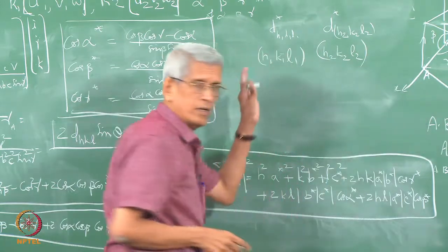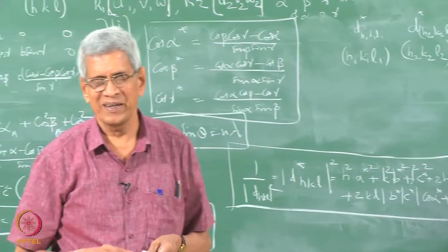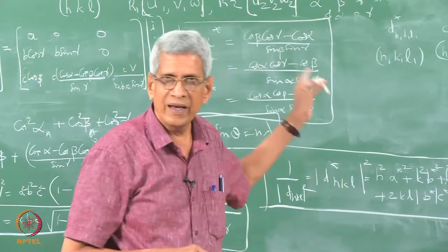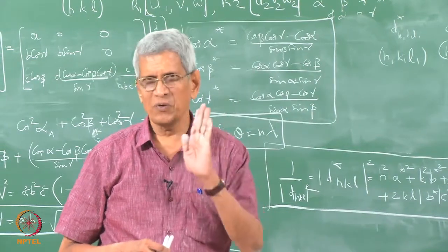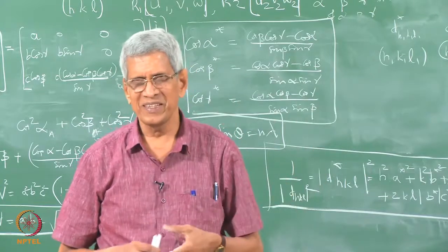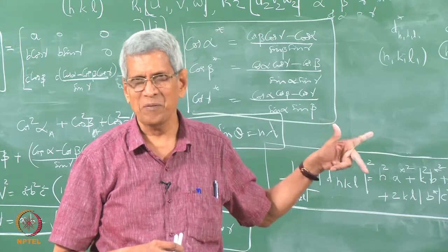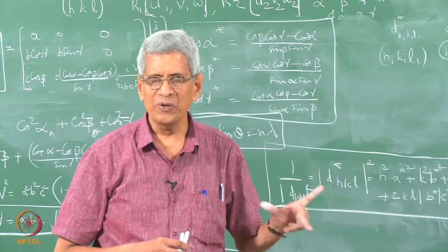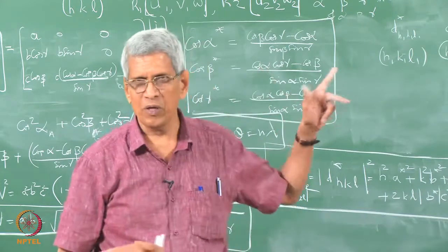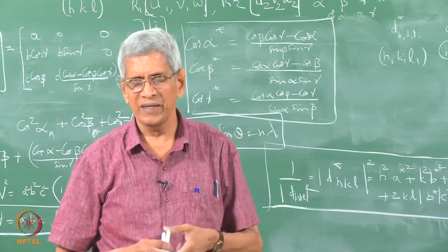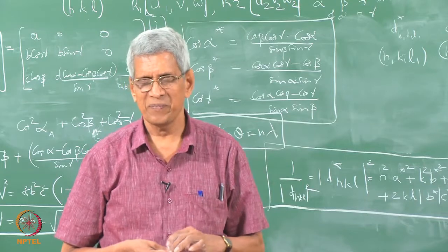If you want to mathematically derive an expression for the angle between these planes, what we normally do is find the plane normal corresponding to each, for which you should know two vectors in that plane. Once we know these two vectors, we find the plane normal for each plane. The angle between the plane normals is what defines the angle between planes.